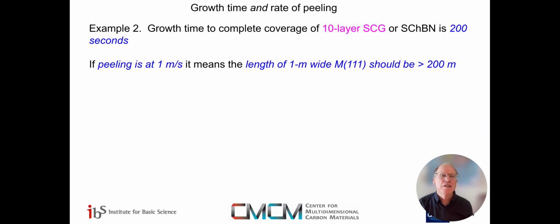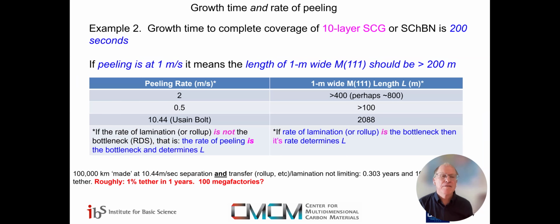Now, with Usain Bolt's pace of peeling, we then have the consideration that 100,000 kilometers, with separation and transfer not limiting, just the peeling is limiting, okay? So this is a big if. Then we're talking 1% of the tether being made in 1 year. And this is doing as well as we can. So that's monolayer though. So I'm sorry, this is 10 layer. So that's monolayer would take 10 years. So even at 10 layer, we have to be really thinking about the scale here. It's a fascinating challenge.